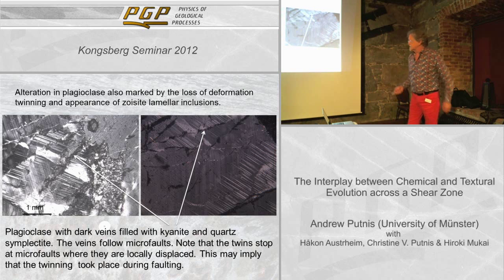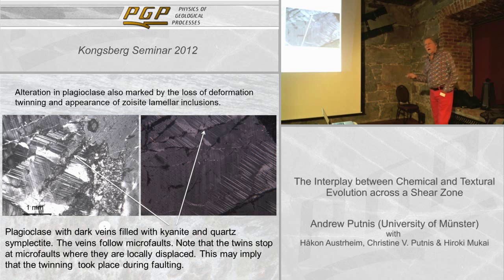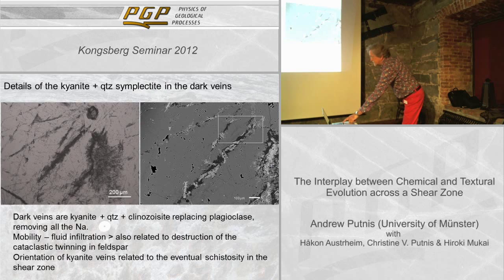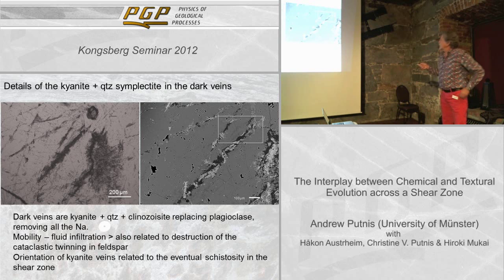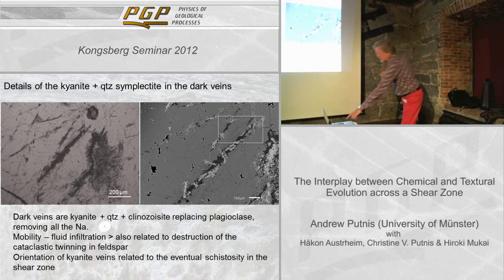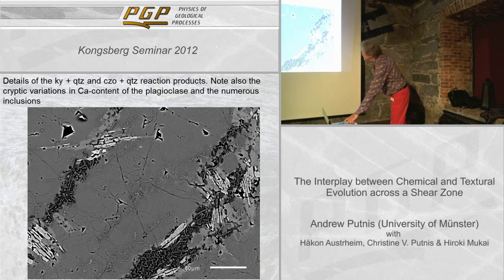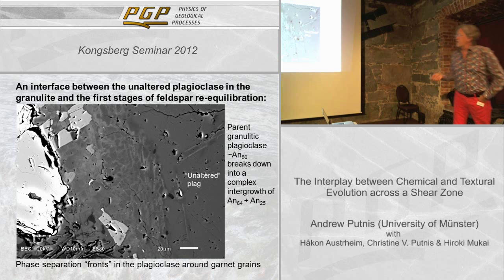What are the earliest signs of fluid-mineral reaction? Well, this is the granulite and it's not very reacted. The first signs of reaction are these coronas, these reaction fronts coming through here. If we look in more detail, we see the feldspar is invaded by myrmekite — it's a two-phase intergrowth — the clinopyroxene is being replaced by amphibole, and this is a sure sign that you've got fluid coming in along this grain boundary. You get thicker and thicker reaction zones — there's no doubt that we have a lot of reaction going on here with infiltration of fluids.